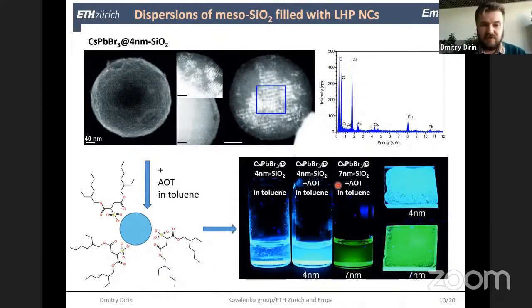Since we use mesoporous silica, we have quite big microparticles, and in order to make them more processable, we wanted to disperse this material better. We show that if we use microballs of this mesoporous silica of about 200 nanometers in size, and we use sodium docusate, abbreviated here as AOT, we can disperse those microballs impregnated with cesium lead bromide nanoparticles in toluene. We wanted to use toluene because lead halide perovskites, as many other halides, are very sensitive and very well soluble in water. So in this case, we prefer anhydrous and non-polar solvents.